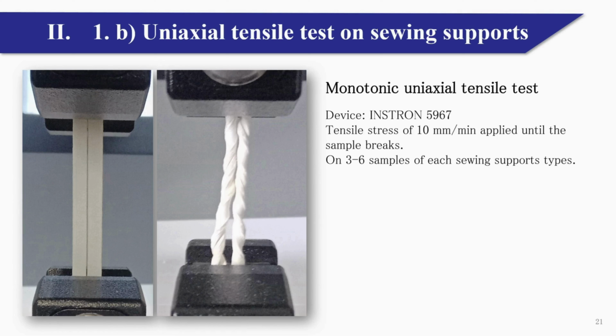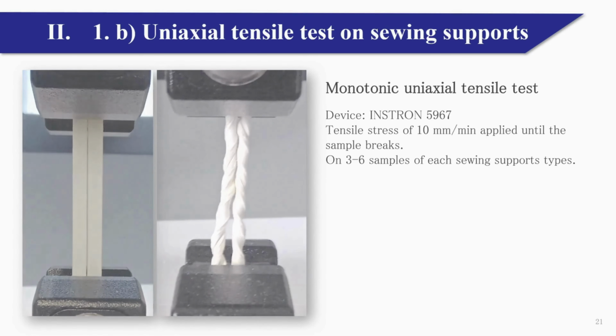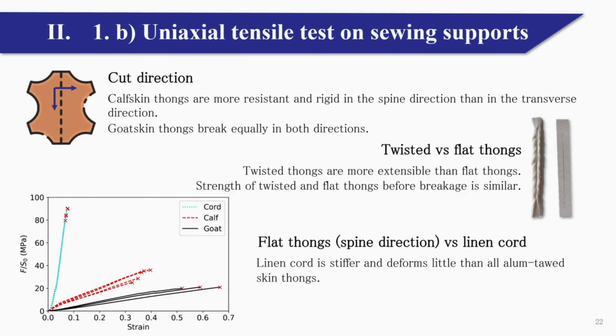A monotonic uniaxial tension test was carried out on the sewing supports. You can see the technical specifications of the test. The obtained results indicate that calfskin thongs are more resistant and rigid in the spine direction than in the transverse direction. In contrast, goatskin thongs break equally in both directions.